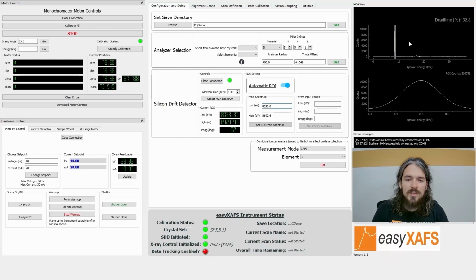So we set a region of interest around that peak. The plot below shows the zoomed in view of that ROI. The sum total of that peak is the ROI counts. Here that's about 204,000. That's the number of X-rays that we want to measure, and we measure that at each step in the scan to build up our XAFS spectrum. I'll set the measurement mode to XAFS, select nickel as the element, and then we can move on to setting up a scan definition to do a quick check on the nickel foil.